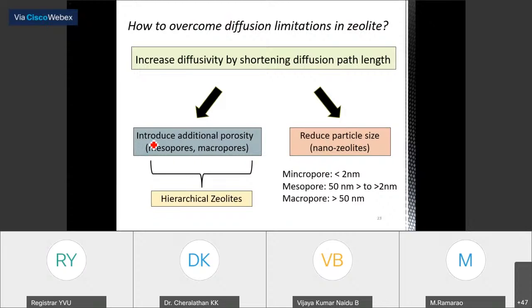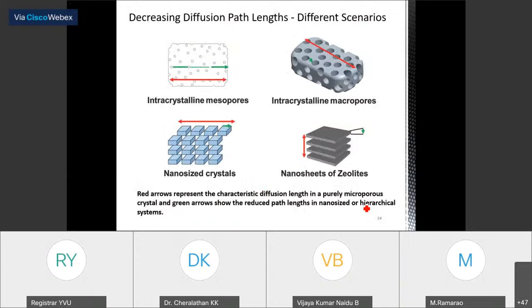If you want to shorten the diffusion path length, we can do that in two ways. We can introduce additional porosity. Already we have micropores in the zeolite, so additional porosity means you have to introduce mesopores as well as macropores. If you introduce this kind of additional pores apart from the micropores, which are intrinsic to zeolites, then they are called hierarchical zeolites. Not only that, you can also reduce the particle size. In that case, they are called nanozeolites. So the scenario can be seen like this: how the diffusion path length is decreasing, and due to which the diffusivity can be improved.